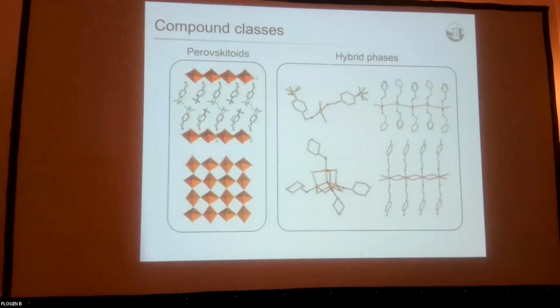So if we look a little bit more closely at the types of compounds that we're seeing, the perovskitoids sort of look like this. I call them perovskitoids because they're not perovskites. And as we get further, they get further away from anything that should be defined as a perovskite. Sometimes we have oxygen, sometimes we don't. So they're pretty diverse. So this is what we see, and you see this sort of distortion that you would expect with copper 2+. These are some of the hybrid phases that we observed, and they look far different, right? And so there's more variability in those phases.